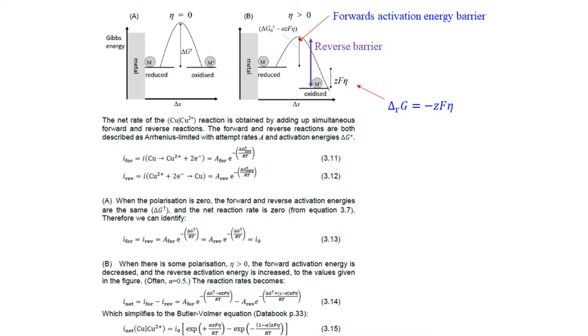The forward and reverse processes are both described as Arrhenius-limited processes, which take place with an attempt rate A, that's A forward and A backward, and some activation energy, delta G star, for the forward and the backward process, respectively. Now, looking at the diagrams, in the left-hand diagram A, we're looking at the case when the polarization is zero, in which case that's the same as saying there's no Gibbs energy change between the metallic state and the dissolved ion. But there is some energy barrier between them when the metal atom has been moved a small distance into solution and it's neither stabilized by being in the bulk metal nor stabilized by being solvated. And this energy increase provides an energy barrier for the polarization is zero case, which we're calling delta G dagger. And this is the same energy barrier going forwards and going backwards.